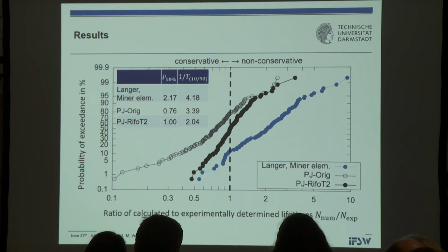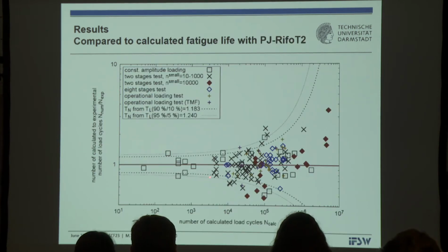The mean value, not to be astonished, is now perfect, and the scatter is small. And the message is we will not be able to improve the accuracy here at all. I will replot in the next figure these numbers here. Keep in mind this is 3.5 or something like that here, and this is 0.5. And if I replot all these numbers, not on the abscissa but here on the ordinate, and I plot these numbers over the number of calculated load cycles to failure, then I get these stars here, so this scatter band. But here in this figure, I have also included constant amplitude testing results with these open squares, and there are some dots spread over there.